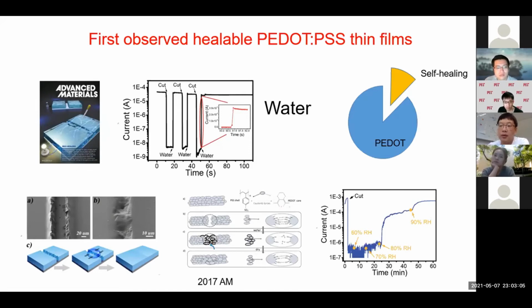As I said, we are not material scientists. We are just engineers and we observed this phenomenon. It works very well. Later on, what we did is we worked with hydrogels. When the hydrogel is very thick, it can be 1 millimeter or even higher. You cut a hydrogel, or you cut a tofu, for example, tofu we bought from the market. I think everyone did it, right? If you cut it, of course, it comes back immediately because of this kind of viscoelasticity or something else.